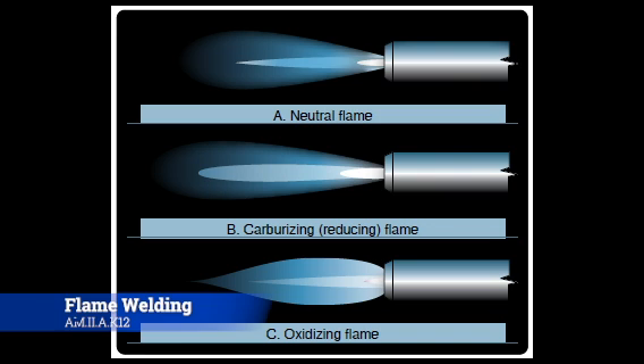However, the carburizing flame in B here burns at approximately 5,700 degrees at the tip of the inner core, and is also referred to as a reducing flame because it tends to reduce the amount of oxygen in the iron oxides. The flame burns with a coarse rushing sound and has a bluish-white inner core, a white center cone, and a light blue outer cone. The flame is produced by burning more acetylene than oxygen and can be recognized by the greenish feathery tip at the end of the cone. The longer the feather, the more acetylene is in the mix. For most welding operations, the length of the feather should be about twice the length of the inner cone. The carburizing flame is best used for welding high carbon steels, for hard facing, and for welding non-ferrous alloys such as aluminum, nickel, and Monel.